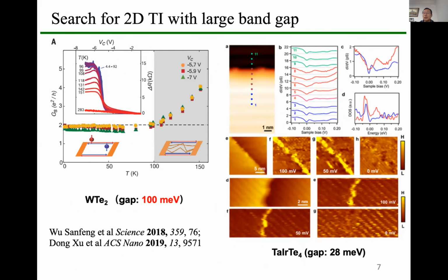Experimentally, it is very necessary to discover new two-dimensional topological insulators with very large band gaps, so that they can be used at room temperature. In recent years, there has been some progress along this direction. A few two-dimensional TIs were discovered. For example, single-layer tungsten telluride was found to be a 2D TI with a band gap of about 100 meV. So the quantum spin Hall effect was observed even at 100 Kelvin.